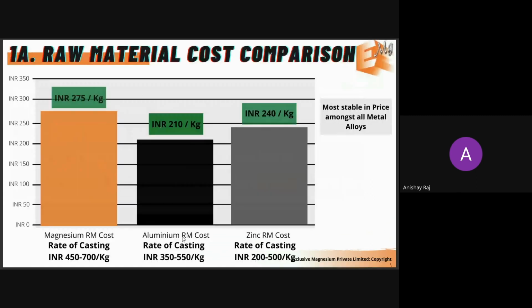So, too expensive. First, the part about costing. You would see that this is an old slide. The price of magnesium is about 240 rupees per kg right now, which is almost equivalent to aluminium. This is also an old slide. Aluminium must be around the 230 to 240 range as well right now. If you see the die casting rates, there's a huge overlap in the cost. Depending on your component, it would cost you anywhere between 450 to 700 rupees per kg, whereas for aluminium, it will be about 350 to 550.